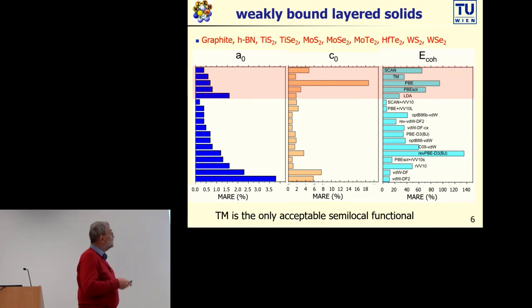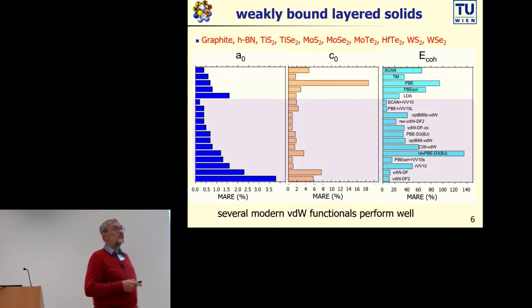On the other hand, if we go to Van der Waals functionals, then first of all we see that Van der Waals functionals not necessarily give you very good results. In particular the original Van der Waals DF methods have even for C large error. The binding energy was very good but for A they are more or less not usable.